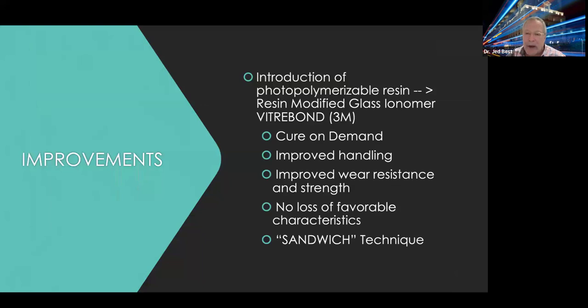So what have been the improvements in glass ionomers? Well, the very first one was the introduction of a photopolymerizable resin, otherwise known as Vitrebond, not Vitremer, Vitrebond. The keys were that you could cure it on demand. It had improved handling because of the resin component of it. And because of the resin component, it also improved wear resistance and strength. And ideally, and in fact, there was no loss of the other favorable characteristics of the glass ionomer. And if you were one of those people that had to make the parent happy by making it look beautiful, you could restore at least the dentin with the glass ionomer and the rest of the enamel with a resin, and that sandwich technique would work very, very well.